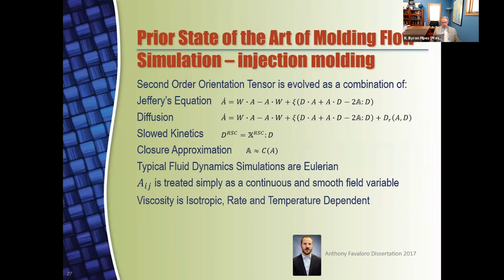However, while it's good for fluid mechanics, it's not as good for our solid mechanics field, where we need the fourth order in order to predict some of our mechanical properties. Anyway, these fluid simulations were Eulerian. This orientation tensor Aij, second order tensor, was treated as a continuous and smooth field variable, but the viscosity is isotropic and rate and temperature dependent. Isotropic viscosity is problematic for us because, as I demonstrated before, we have a highly anisotropic viscosity tensor in the real world. And further, as the deformation occurs in the molding, viscosity should be responding to orientation state.